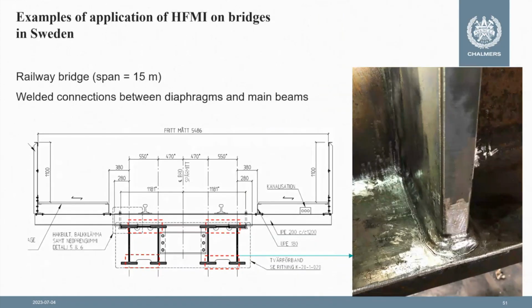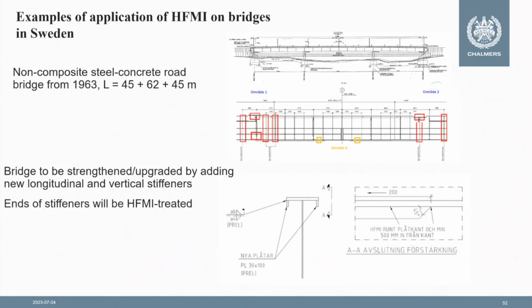Another railway bridge where critical welds between vertical stiffeners or diaphragms and bridge girders for a short-span railway bridge were also treated. This is a new bridge. And this one is an existing bridge built in 1963, which needed strengthening by welding longitudinal and vertical stiffeners on flanges and webs in different locations. And the ends of these stiffeners were critical with respect to fatigue. So HFMI treatment will be applied now in the summer, in the coming 2 weeks, on these details in order to enhance the fatigue strength and fatigue performance.